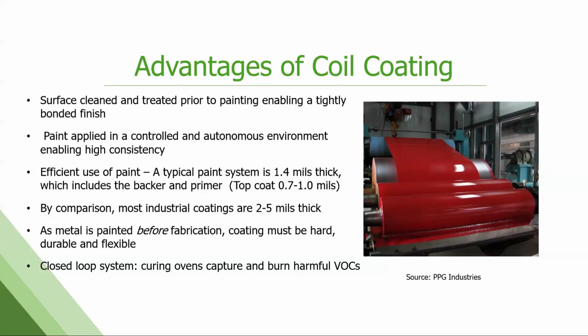And all this done again before fabrication. So this paint has to be both hard and also flexible at the same time, so it can make finished parts. So there's a lot of science and research that goes into that. These are closed loop systems. We are using solvent-based paints, but all of these paint lines are capturing those fumes and incinerating them, actually generating heat through a thermal oxidizer to pump fuel and energy back into the line. So the final product is zero VOC.